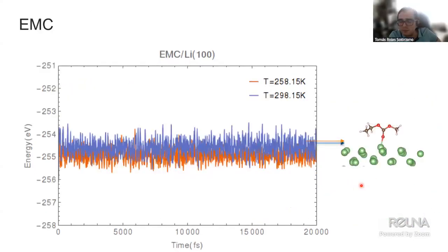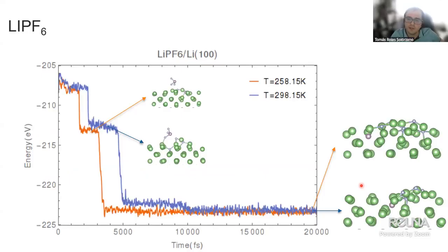On the other hand, the EMC doesn't seem to be affected by the temperature at all. It just simply comes and attaches to the surface and remains the same for both of the cases with almost identical energies. And the LiPF6 does show, again, a significant difference in the decomposition process, but it shows almost identical end products, which is the absorption of the phosphorus and a layer of lithium fluoride on the surface. In this case, it's almost like a mirror effect for both of the temperatures, but one of them does it earlier. And again, that seems to happen at the lower temperature, which is not what you would expect. You would expect that the higher temperature helps the reactions to occur faster.